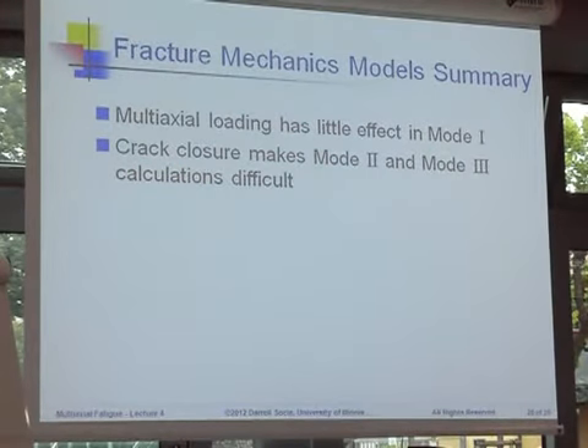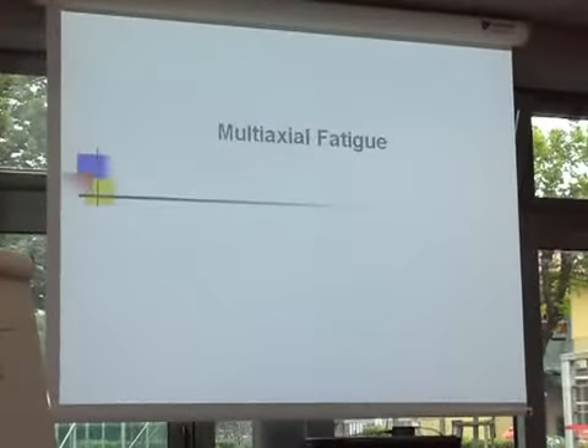The only opinion I have on all of this is my observation that cracks grow in either mode 1 or mode 2, or mode 3 in torsion. I've never seen a crack growing in mixed mode for very long. Cracks always try to either stay in mode 2 or they try to grow in mode 1, and they never grow at some combination of mode 1 and mode 2. They always move towards one or the other. That's the only observation I would make. So I always stop here, having given you an idea of what's happening in the fracture.